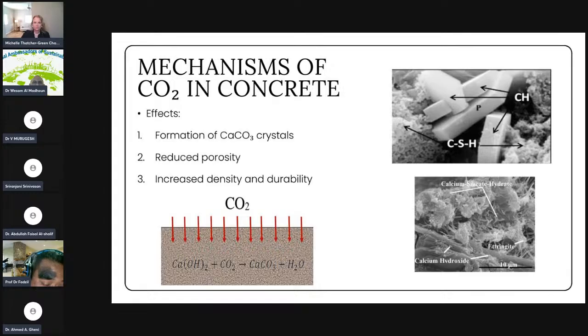So the concept of introducing CO2 into the concrete is identified as one of the best methods to overcome the issue of calcium hydroxide. From the research being carried out, it is identified that by introducing CO2 into the cement matrix, the CO2 has successfully transformed the calcium hydroxide to calcium carbonate. The occurrence of calcium carbonate instead of calcium hydroxide has been identified to reduce the impact of calcium hydroxide and at the same time reduce the impact of porosity due to the formation of calcium hydroxide before. So this is a great finding from the research being carried out.